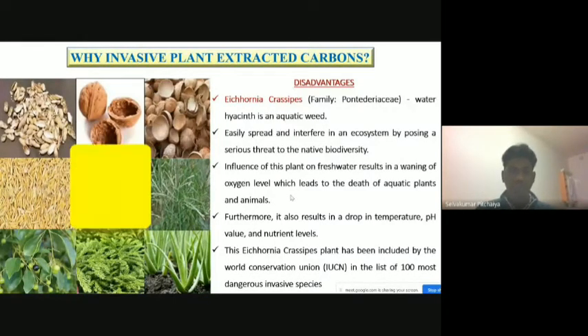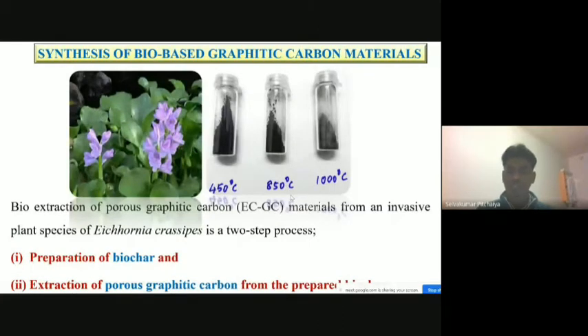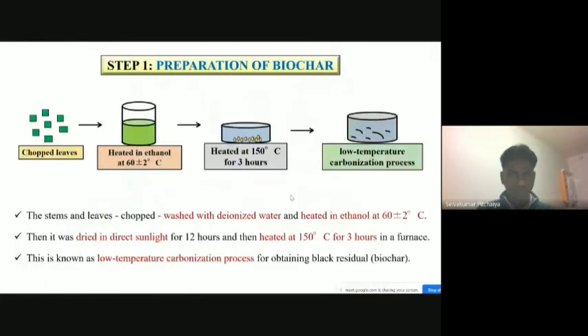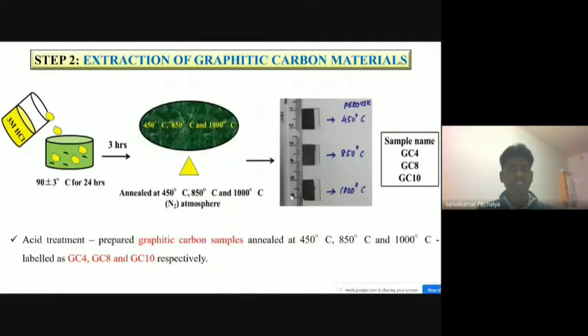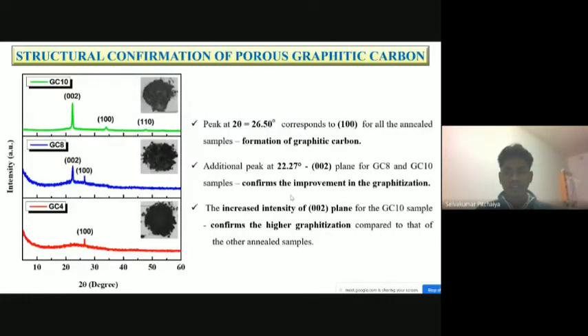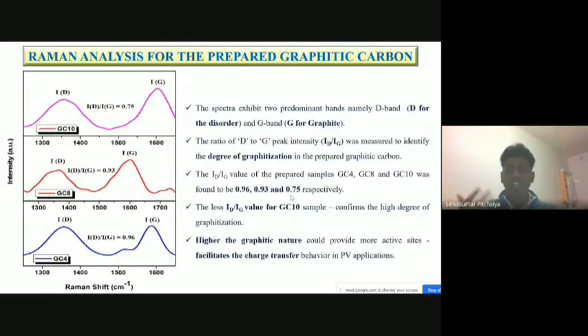We extracted carbon from this plant using a two-step process. The first is a simple low-temperature carbonization heating process, and the second includes acid treatment and heat treatment, with various annealing effects with respect to time and acid treatment. This is the structural confirmation, where we obtained graphitic carbon. If you get higher graphitization, your devices will function better. It facilitates charge transfer in photovoltaic devices, and this is confirmed by Raman analysis as well.